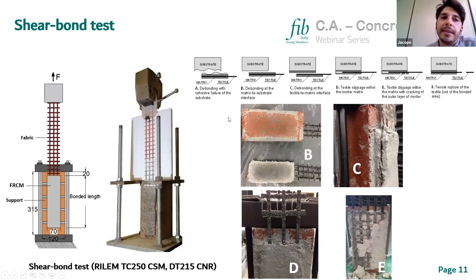So another important test is the shear bond test. In this case, we apply a strip of the FRCM to a substrate, which can be a masonry substrate or concrete. And then we apply a shear load, and we can have different failure modes. The failure modes depend on the type of substrate and how we prepare the substrate and on the bond between the mortar and the substrate, and of course, on the bond between the fabric and the mortar. So in this case, we can have debonding at the textile to matrix interface or fabric slippage within the mortar, or we can also have the rupture of the fabric.